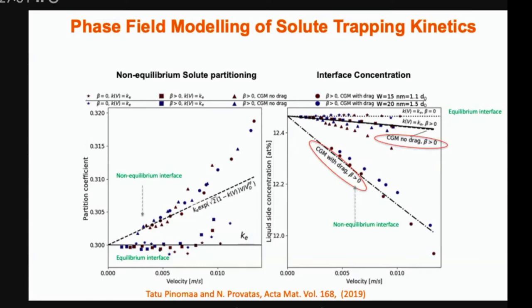We track interfaces and match what the composition is on either side of the interface. On the x-axis is velocity. The horizontal line up to some velocity shows all the data from our simulations scattered around the black line. The black line, KE, is the equilibrium partitioning coefficient. So it means that up to some point, your model is, if you force your model to pretend it's in local equilibrium, it'll maintain a local equilibrium of the solid concentration ratios. With this new model I showed you on the previous page, basically now your simulation data starts to follow this slanted line. That slanted line comes from this non-equilibrium continuous growth model of Cahn's.